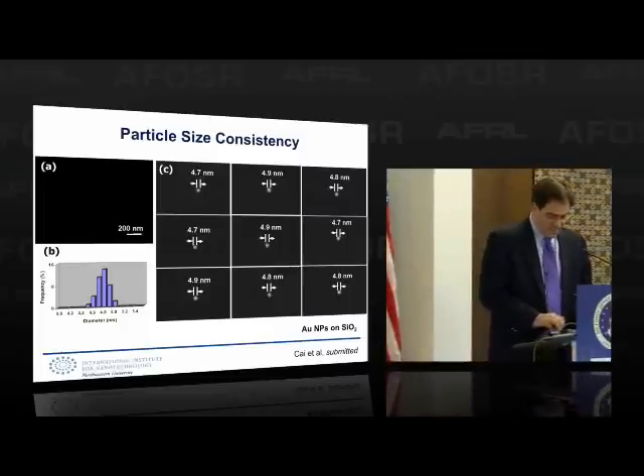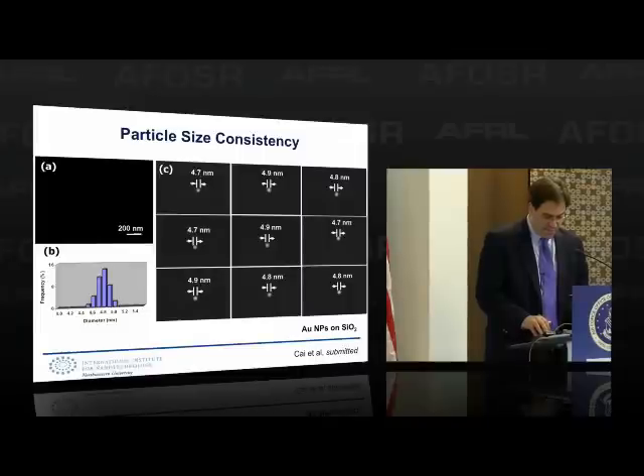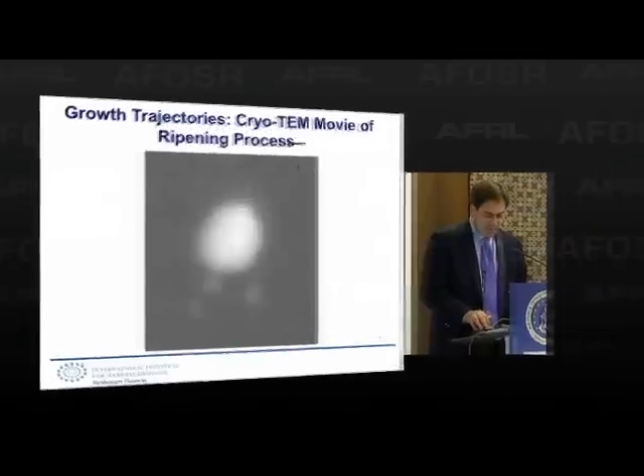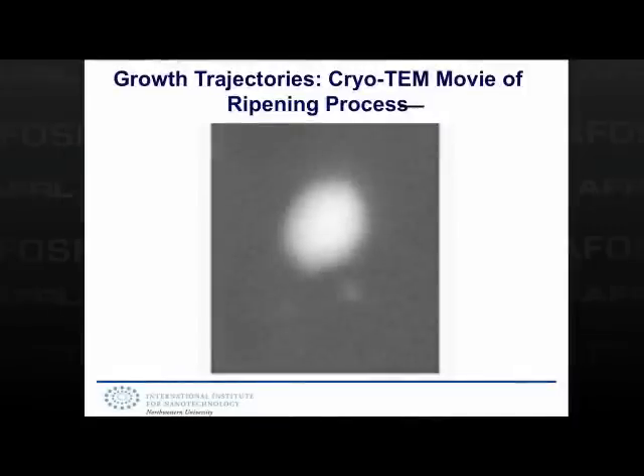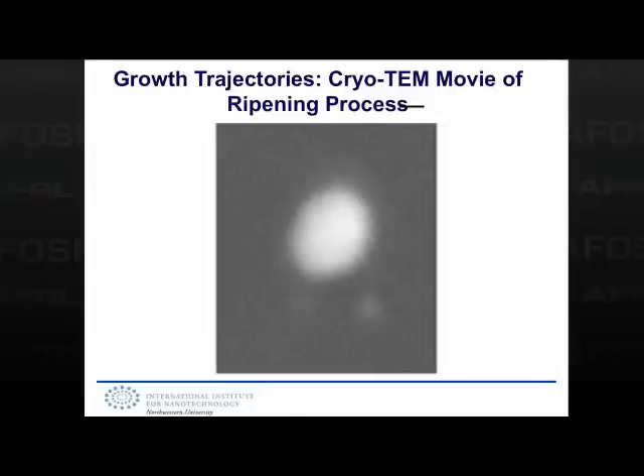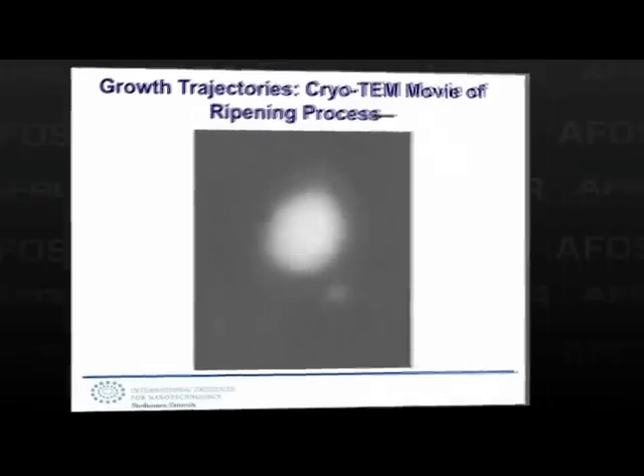And now we're going to be able to look at this in real time by cooling it down. And I want to just make a point here. If you look at this, this is low temperature electron microscopy images, and you're going to see there are particles over here. We're watching the particle grow over time. It's going to eat this particle. And you're effectively watching coalescence and Ostwald ripening occur by fixing the size of the reaction vessel, in this case, the polymer feature, and then cooling it down and allowing the system to basically coalesce.